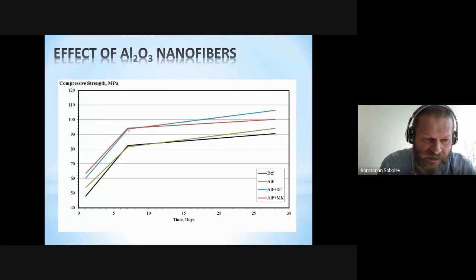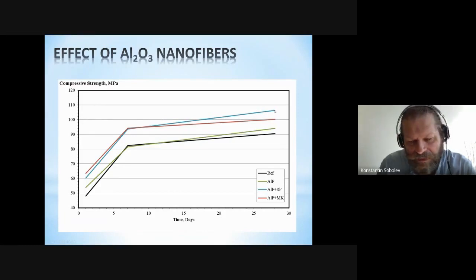And you can see that early age strength was considerably increased, and the 28-day strength was considerably increased. Metakaolin worked better for early strength, silica fume worked better for longer term strengths. But look at this difference: for compressive strength of 90 megapascal, it was improved by 15 megapascal. This is really considerable improvement.